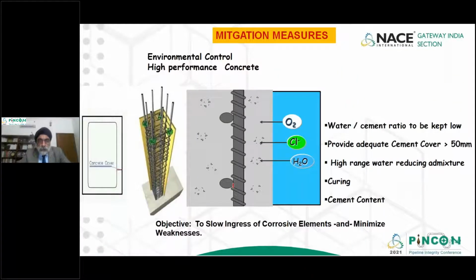So the first strategy which a company would look at is to use a high performance concrete which would inhibit chloride, oxygen and moisture from traveling into the concrete cover and causing the loss of the passive film of the rebar. Again, there are various strategies which can be used: to have a proper water cement ratio, to provide adequate cement cover, to have a high range water reducing admixture, curing the cover properly, and having a proper cement to water ratio, which I've already mentioned above.